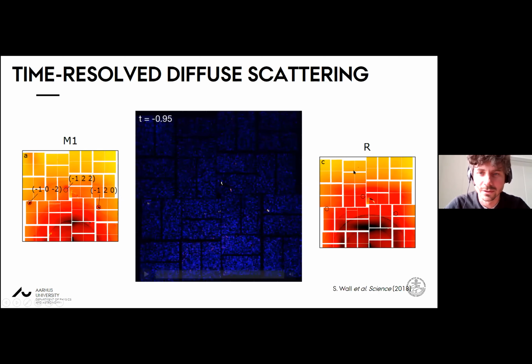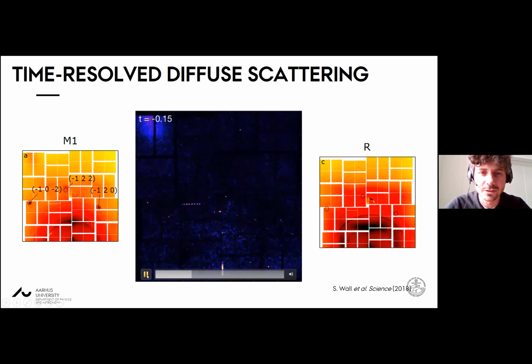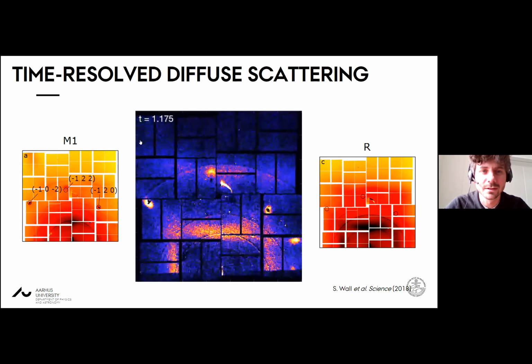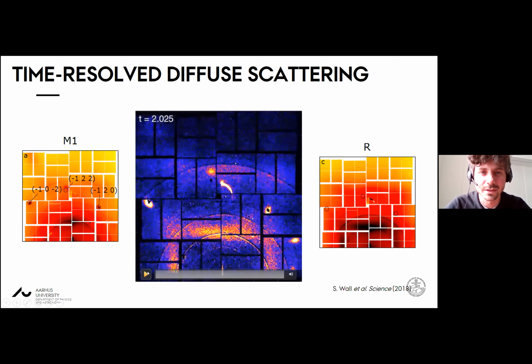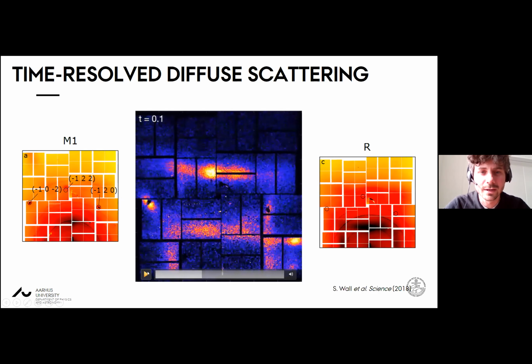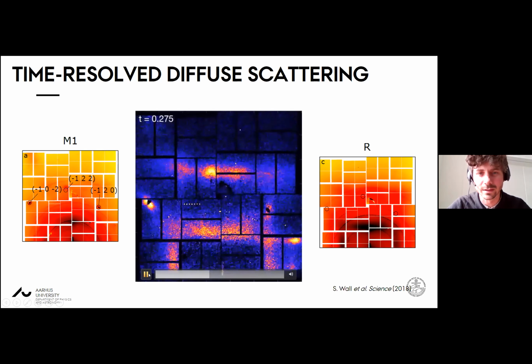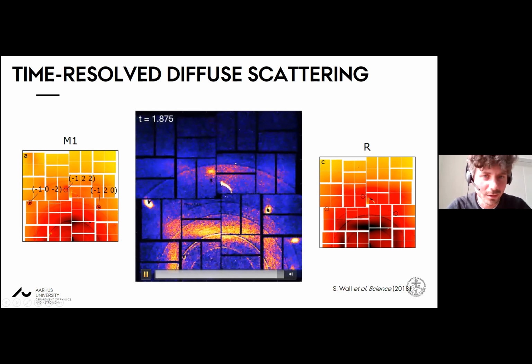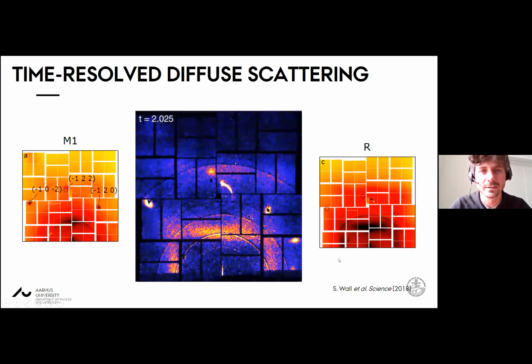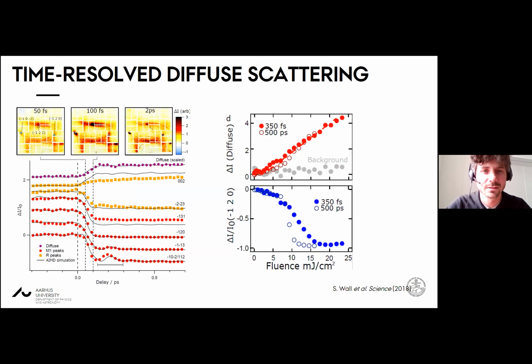So, okay, I'll show you the summary of the left and the right. And we're going to watch a video now. You have to pay attention because it's very fast. On the top left is time, in picoseconds. I'll show it again. I stopped the video at 100 femtoseconds, and you can see there's already very strong diffuse scattering in the positions that we were expecting it to appear. Then it's stable for a long time afterwards, and actually continues to be stable for many hundreds of picoseconds.